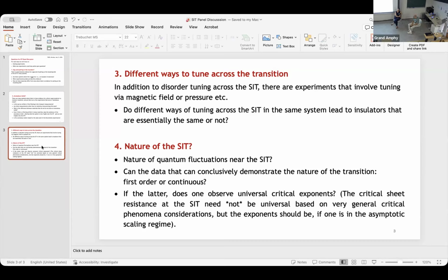And in indium oxide, this metal state, whatever you want to call it, has not been observed, I don't think, either in thickness or in the field or ever, and under pressure we see it. So how much pressure do you apply? Gigapascal. So 10 gigas. So this is hydrostatic pressure on a thin film. Is that what you're doing?